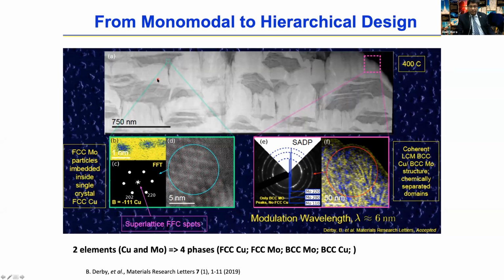So this is copper and moly that has been co-deposited at 400 degrees C. And with just two elements, we are seeing four phases. So there are two kinds of composites giving rise to a total of four phases. There is the composite that forms a matrix, which is the lighter structure that you see here, the lighter background. So this is a Z-contrast image. So the more moly-rich region is the matrix. And the matrix is shown by that pink square.